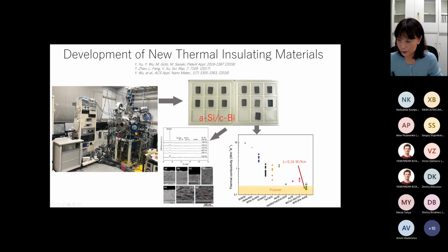And here, the green triangles are our result, and the others are the thermal conductivities reported in previous work. We can see that for the inorganic nanocomposite, we get a very low value, lower than the previous work. And actually, our lowest thermal conductivity, 0.19, is quite similar to a polymer. Polymers are usually considered to have much lower thermal conductivity than inorganic materials, but with our inorganic nanocomposite, we can obtain a thermal conductivity very similar to a polymer.